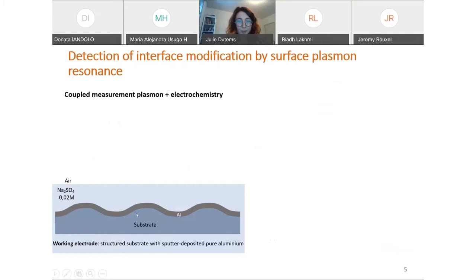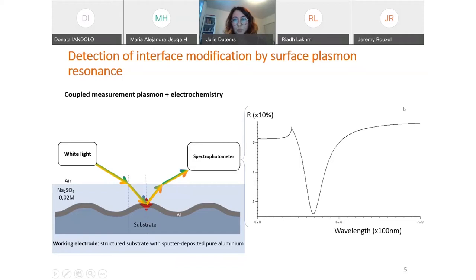As I told you, in this thesis I'm using a diffractive grating: a structured substrate with sputter-deposited pure aluminium that will be dipped in an electrolyte. A white light will be incident on our grating. The surface plasmon will propagate at the interface, and the spectrophotometer will observe the surface plasmon. And when we have a modification at the interface, hence the growth of a passive film, there will be a modification in the resonance wavelength. It is this variation that will be used in order to know what modification has been done at the interface. And so the more, for example, a passive film grows, the more we will observe a variation in the spectrum observed by the spectrophotometer.